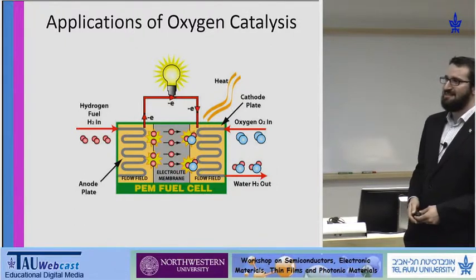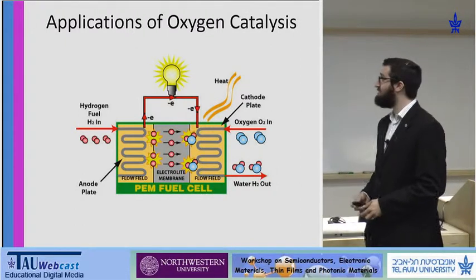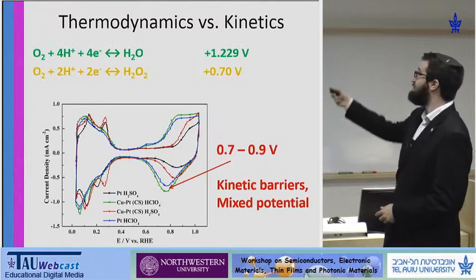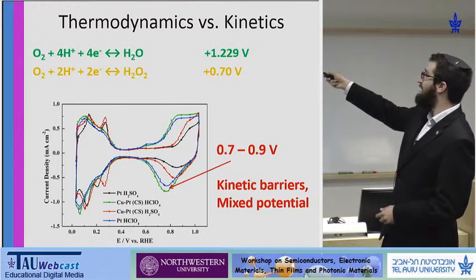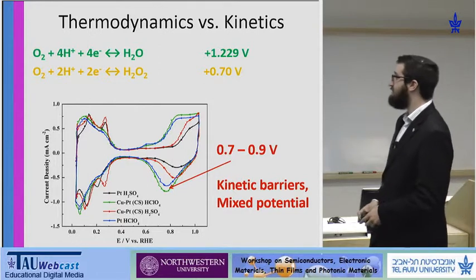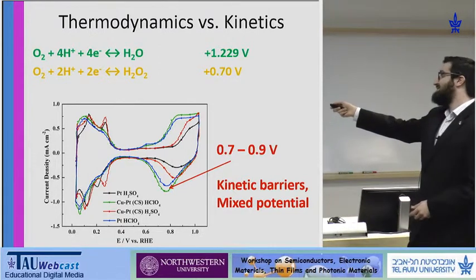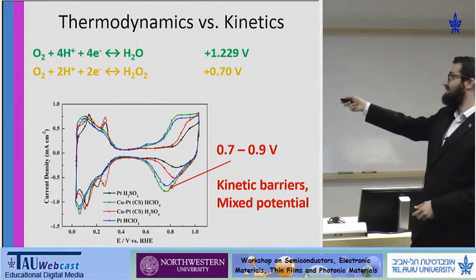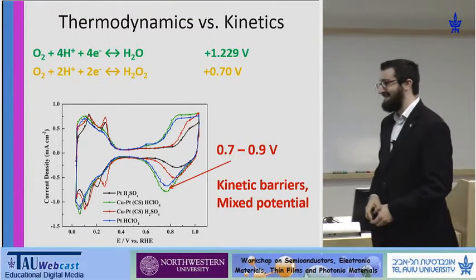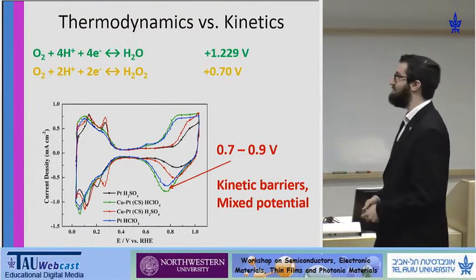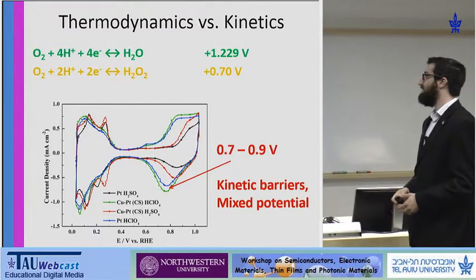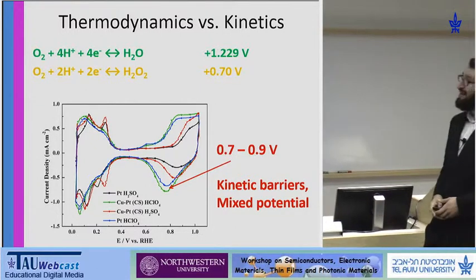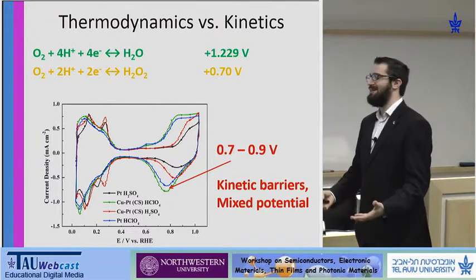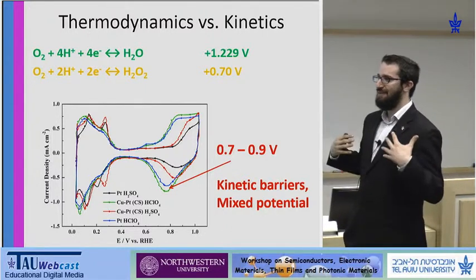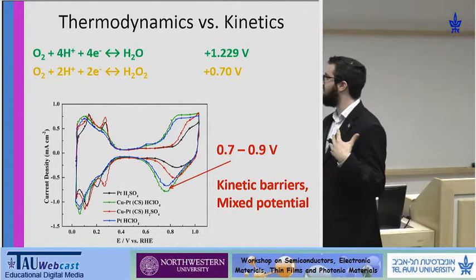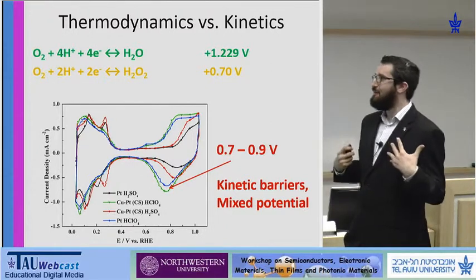The problem is that the kinetics of this reaction are extremely slow, and even though thermodynamics would predict the voltage of the cathode being 1.22 volts, in practice, we usually see this reaction between 0.7 and 0.9 volts, and it's this kinetic barrier that's leading to this drop, which is effectively an overpotential. Right now, platinum is used. And what we want to do is design materials that are not platinum to drive down the cost of fuel cells. But platinum is the most active.